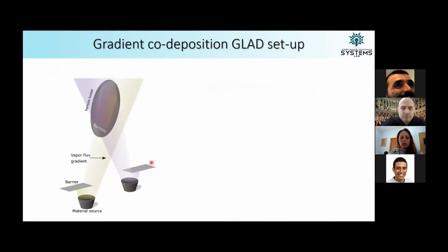deposition chamber. So in order to increase the complexity now, we inserted two sources, one across from each other, both with optimized barrier positions to obtain the linear gradient flux in our vapor in the PVD system. And then we co-deposit two different materials. But then we say, okay, this is just a binary system. We want a multinary system where we can have a lot of different elements and study all these different elements.